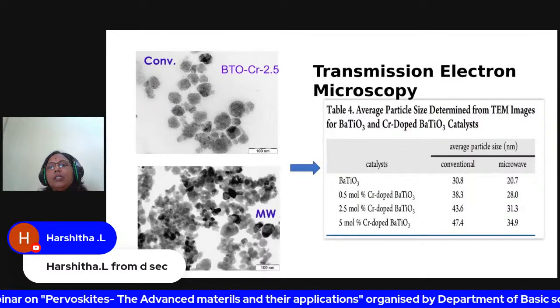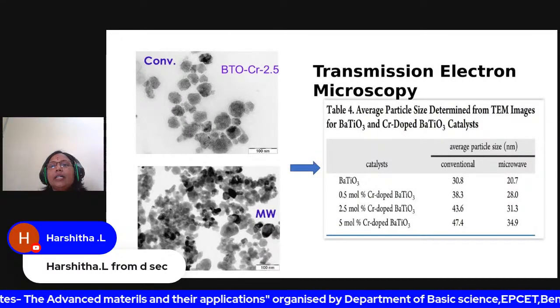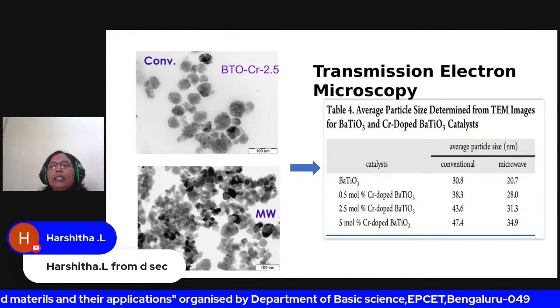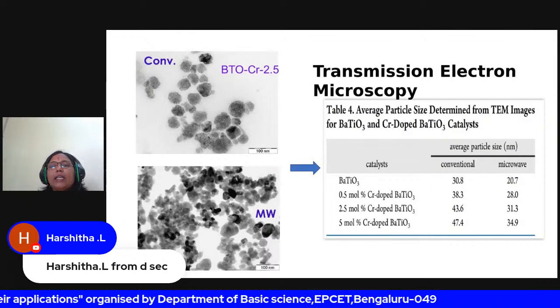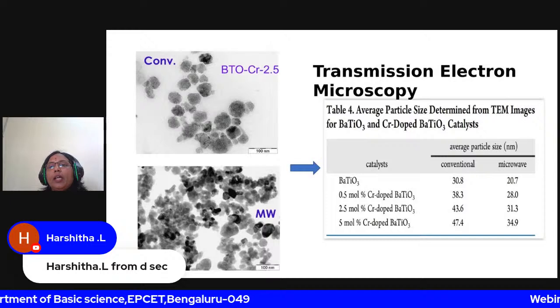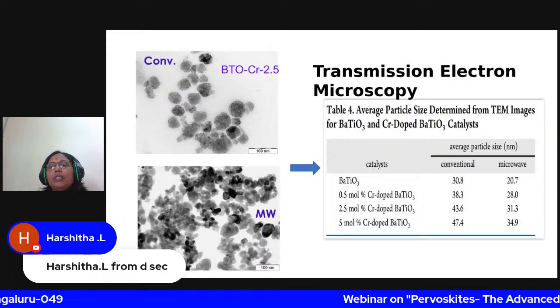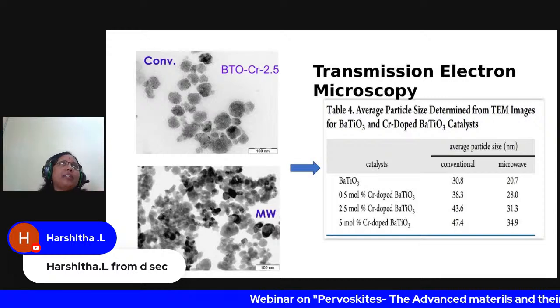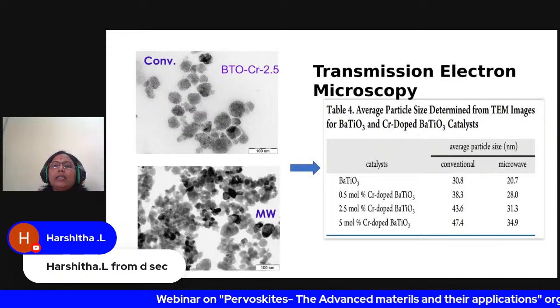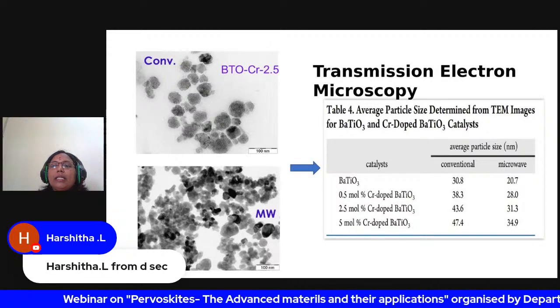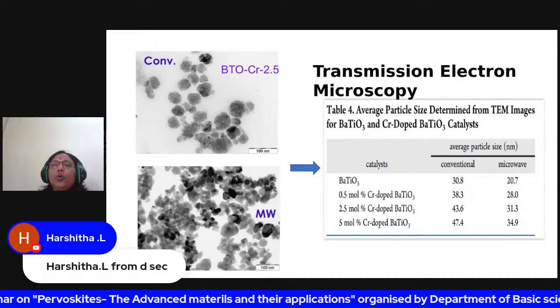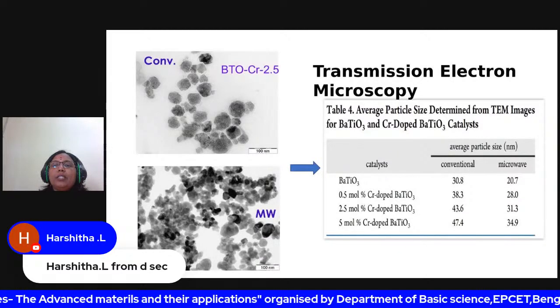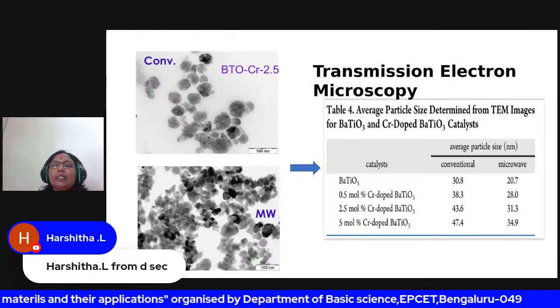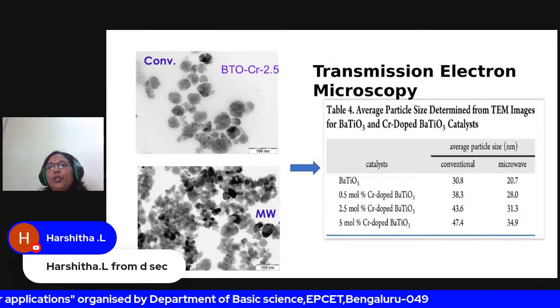So conventionally synthesized barium titanate is 30.8 nm, and the crystallite size of chromium samples increased with increasing chromium content, whereas in the microwave synthesized sample, you can see here it is just 20.7 nm. However, the particle size increased with increase in the chromium content of the sample. But if you see, almost 10 nanometers difference, it is huge.